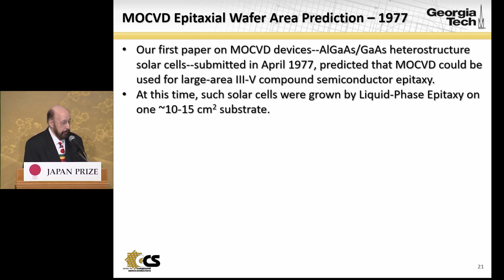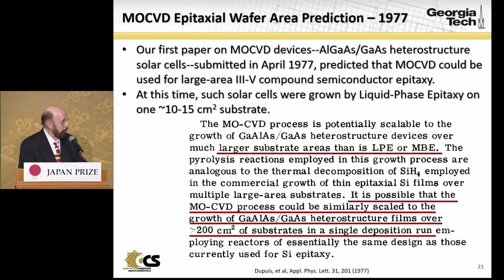In 1977, our first paper on MOCVD devices, which were aluminum gallium arsenide heterostructure solar cells, predicted that MOCVD could be used for large area III-V compound semiconductor epitaxy. At this time, solar cells of this kind were grown by liquid phase epitaxy on one substrate on the order of 10 to 15 square centimeters per wafer. I predicted that larger substrates could be used in the MOCVD process, larger than LPE or MBE, molecular beam epitaxy, and that it's possible that this process could be scaled for these heterostructures to greater than 200 square centimeters of substrates in a single deposition run.